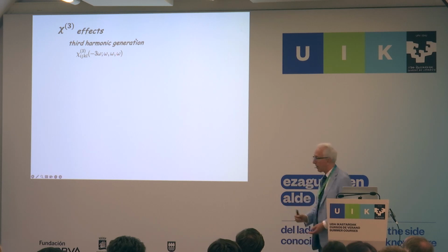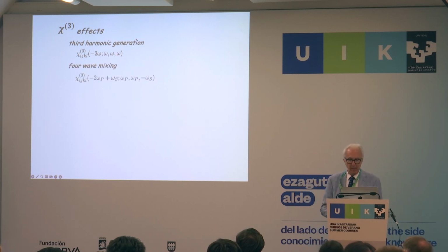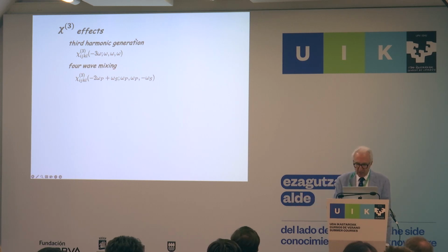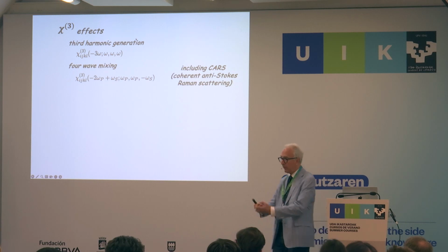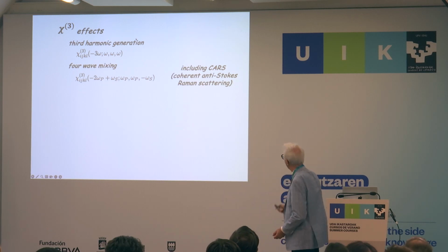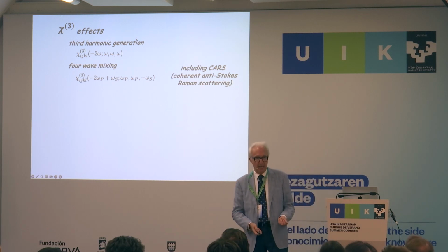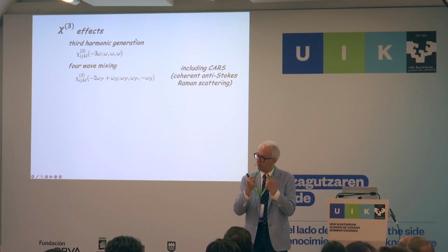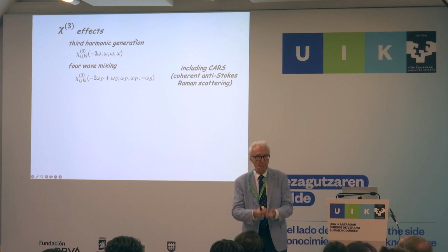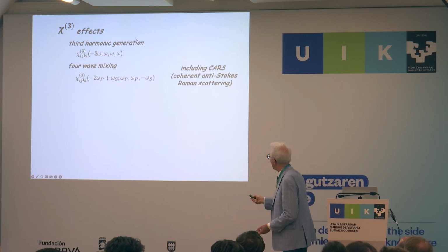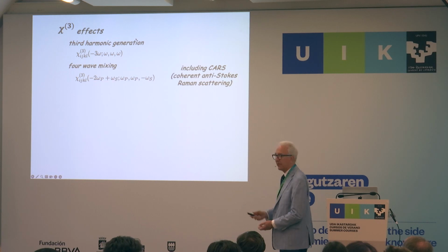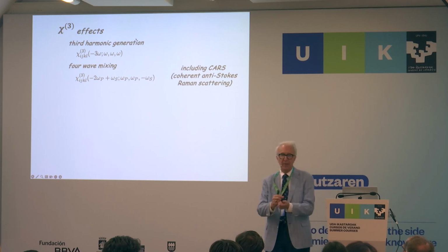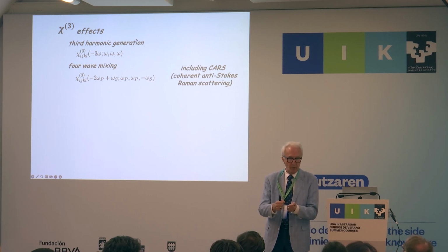Here's third harmonic generation, as we mentioned. Okay? Here's the 4-wave mixing one I talked about. And actually included in this, if you're dealing with molecules, is something called CARS, coherent anti-Stokes-Raman scattering. You can drive the vibration of a molecule. You can drive a phonon in a crystal in the same way, okay, by coming in with a strong pump field and a signal field like this, okay? And you want omega p minus omega s to be the vibrational frequency you're trying to drive, okay?